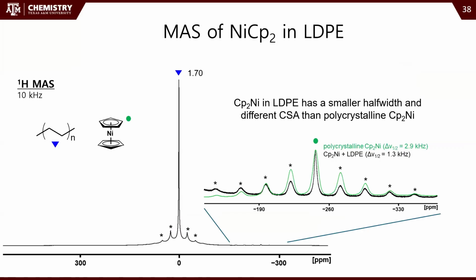So the dry material shows a chemical shift anisotropy. This is proton NMR, right? So it's shifted way over because it's paramagnetic. This is the nickelocene (NiCp2) signal. And so it has a chemical shift anisotropy, but it's different from the polycrystalline material, and it has a reduced half width. And so what that's telling us is that it's not the same crystal packing structure, right? So it's either discrete molecules distributed throughout the LDPE, or it might be co-crystallizing with the LDPE or something like that. But it's definitely not just nickelocene (NiCp2) crystallites embedded in the material.